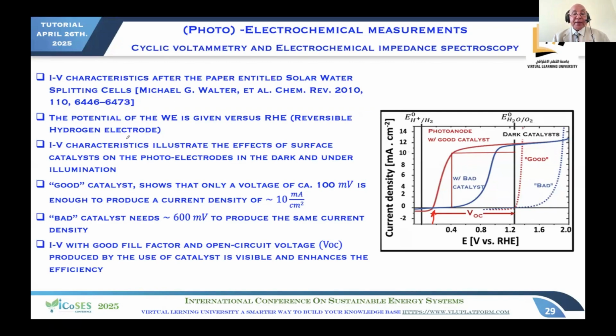You see here that this good catalyst shows that you get 10 milliamp per square centimeter with just 100 millivolt. In contrast, you need 600 millivolt in order to produce exactly the same. And therefore, for the production of oxygen, you really need a good catalyst in order to make your reaction.